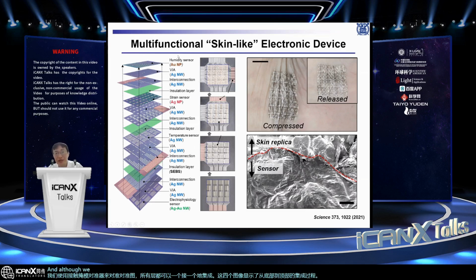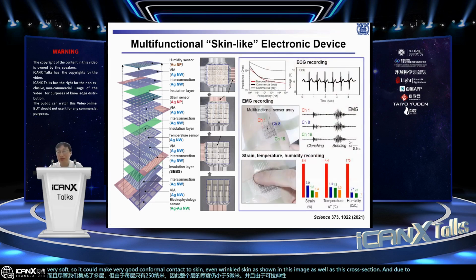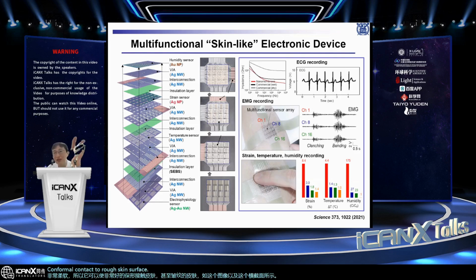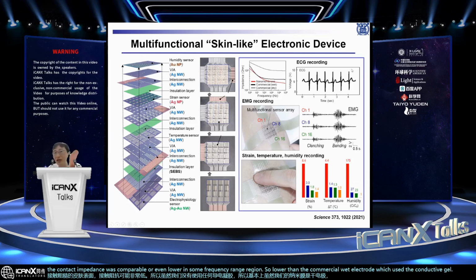And although we integrated multiple layers, since each layer is only 250 nanometer, the entire layer thickness is still less than 5 micron. And since the stretchability is 1000%, it is very soft, so it could make very good conformal contact to skin, even wrinkled skin, as shown in this image, as well as this cross section. And due to this very good conformal contact to rough skin surface, contact impedance could be very low. Although we did not use any conductive gel, so basically, our nanomembrane is a dry electrode, the contact impedance was comparable or even lower in some frequency region than the commercial wet electrode, which uses the conductive gel. So due to this low contact impedance, we could record ECG data or EMG data with high quality.